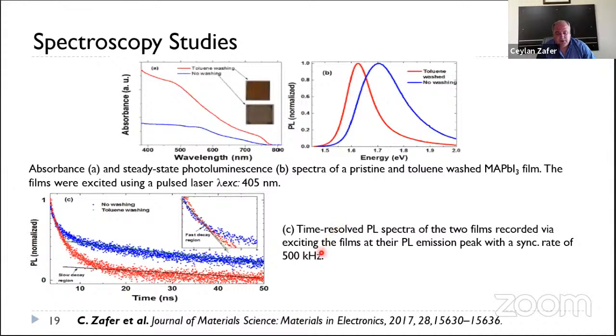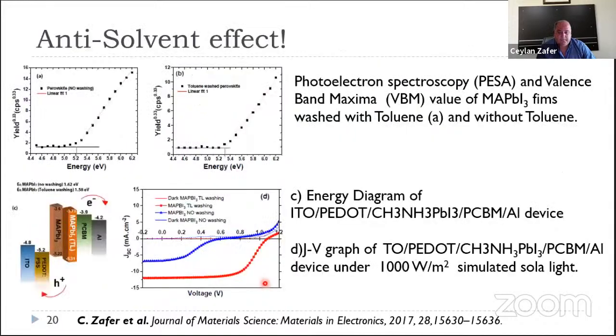If you look at the charge dynamics and the photophysics, what's going on deep in this material, comparing the washed and non-washed films, we will see the dynamics are also changed in the material. With the washing of the material, the decay of the excited charges becomes slower. And this means we will have less, or slower, recombination in the material.